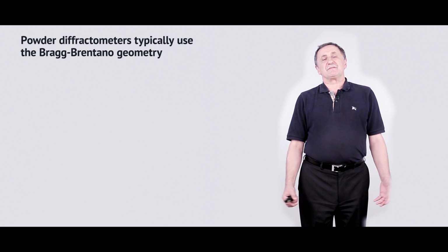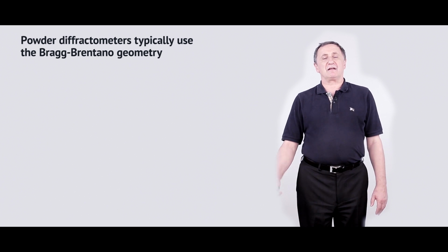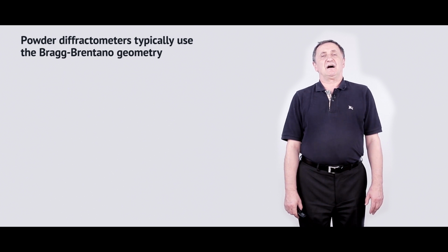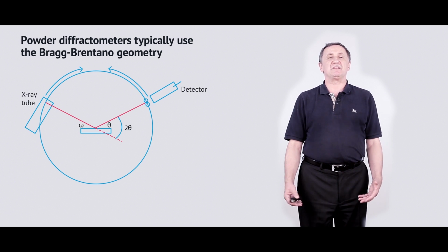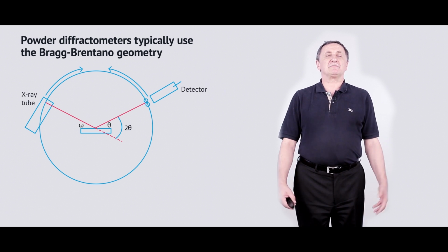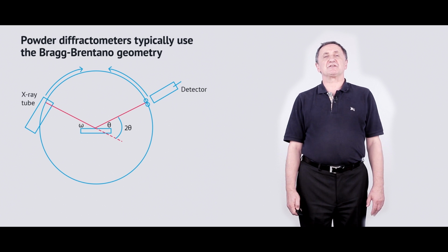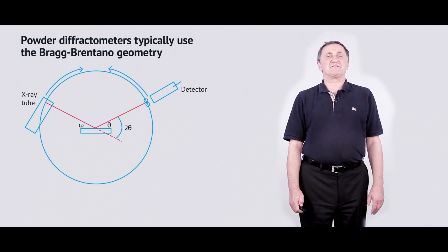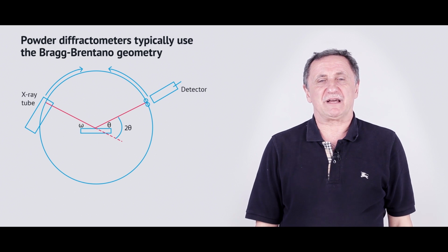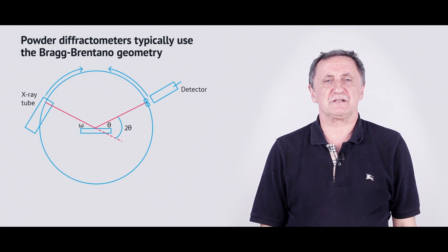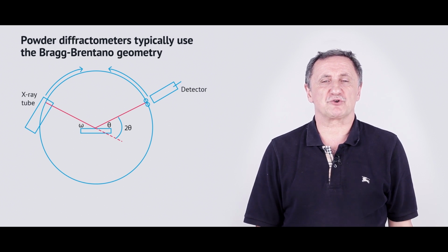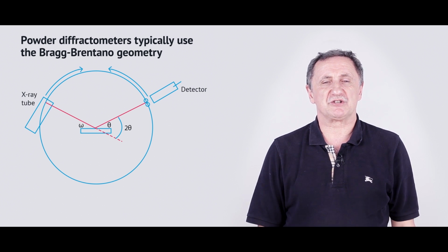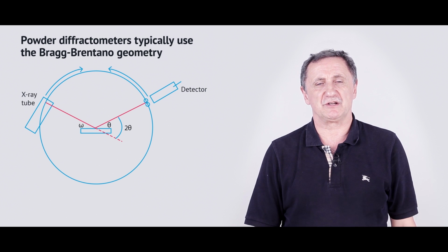Of course, there is not one but many parallel hkl planes in our material, and because of that we can talk about first order reflection, second order reflection, which means we expect not one but several peaks corresponding to reflections between these selected hkl planes. All right, on this screen you can see the schematic of the powder diffraction Bragg geometry. So what do we have? For sure, we have the X-ray tube, which radiates X-rays with a known wavelength.